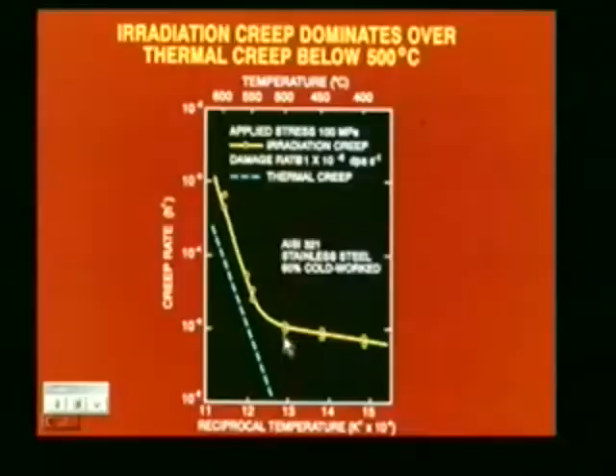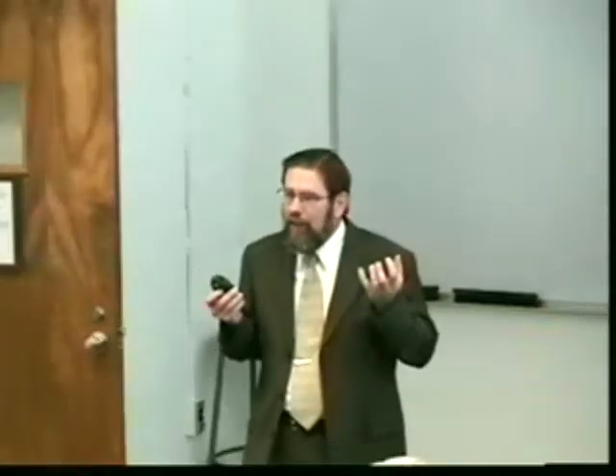Now, I said it was not a high temperature phenomenon, and here we have creep in stainless steel as a function of temperature, and in thermal creep we have deformation, but when we get down below, in this case, 500 degrees, it becomes insignificant. And we know that when we keep metals around at room temperature, they don't deform. The Eiffel Tower has been standing since 1889. It doesn't bend over and collapse.